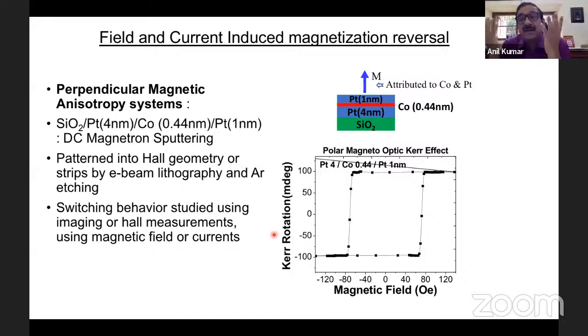I can do a vibrating sample magnetometer measurement or a SQUID magnetometer measurement for magnetization. Here, what I chose to do is something called Kerr rotation. Suppose I have plane polarized light hitting the surface of a material, and there is a reflected light. If it is a non-ferromagnetic material, or the material has net zero magnetization, the plane of polarization will remain the same even after the reflection.